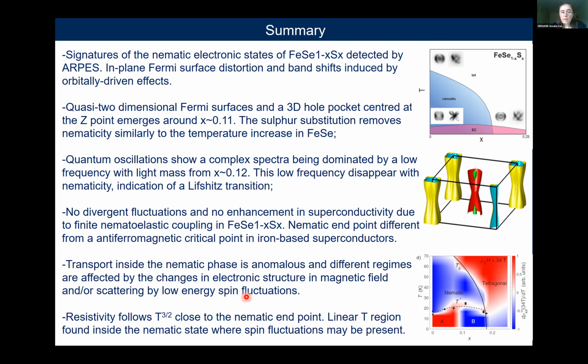And what we found in high magnetic field studies is that the transport is anomalous inside the nematic phase. There is a region of linear T, but we find a very extended T^(3/2) close to the nematic endpoint, and where the spin fluctuation may be present. Well, thank you very much, and I'm looking forward to hearing your questions.